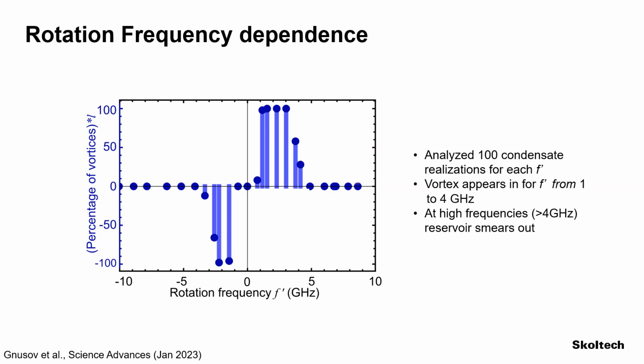repeatability. If I go even faster, what happens is that the exciton reservoir that I inject has some lifetime of the order of a few hundred picoseconds. And now what I do, I smear this dumbbell that I was rotating so that practically for polaritons it becomes a perfect circle. And then again, in the perfect circle, there is no torque and there are no polariton quantum vortices forming. So this work was published actually just a year ago with Ivan Gnusov and Sergei Alatin and theory from